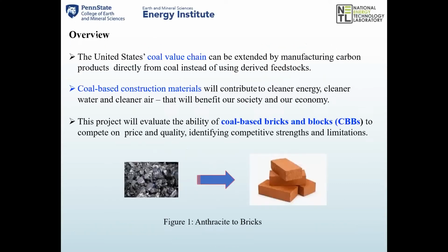So just an overview, the United States coal value chain can be extended by manufacturing coal products directly from coal instead of using derived feedstocks. Coal-based construction materials will contribute to cleaner energy. If one considers that a traditional clay brick is fired at 1600 degrees F to 2400 degrees F for 10 to 40 hours, and our bricks, all we do is melt the thermoplastic binder. So they are fired between 300 and 500 F for about a half hour. So this project will evaluate the ability of coal-based bricks and blocks to compete on price, quality, identifying competitive strengths and limitations.